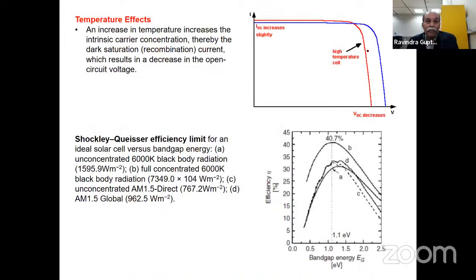What is the effect of temperature? When we increase the temperature, we increase the intrinsic concentration and also increase the dark saturation current because of recombinations. So it reduces the open circuit voltage. This means high temperature is not good at all. For the silicon-based solar cell, temperature should be low.